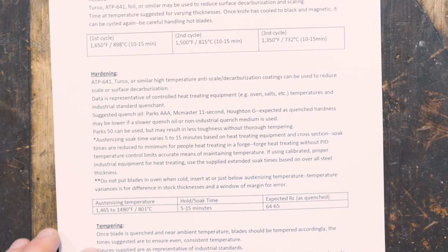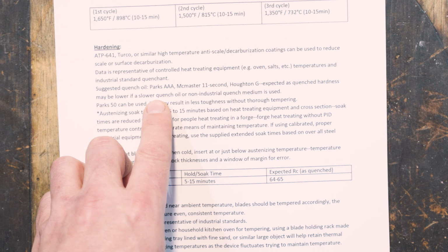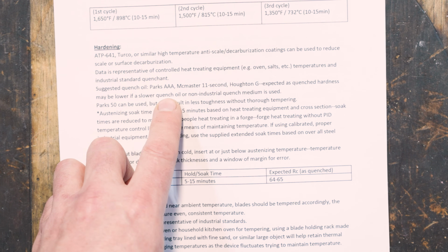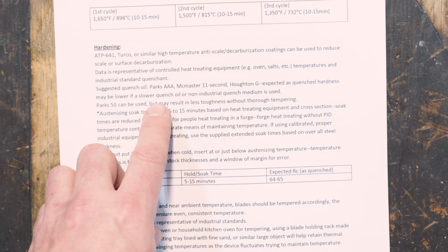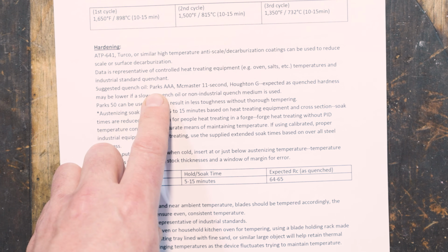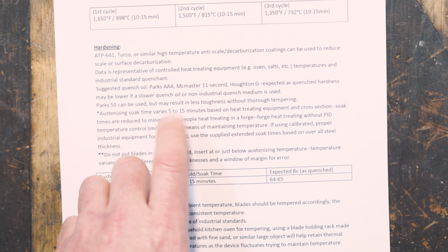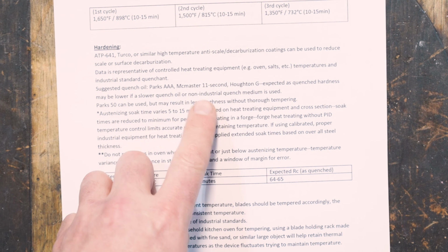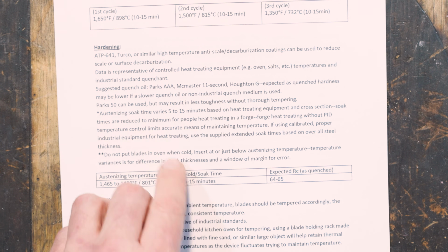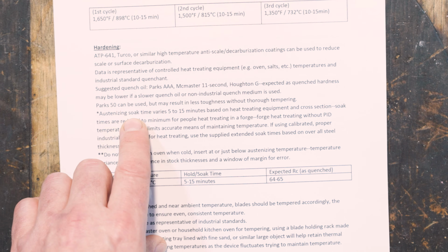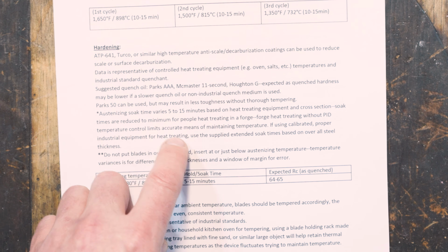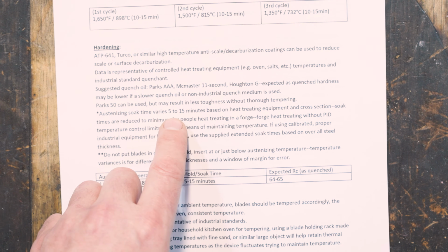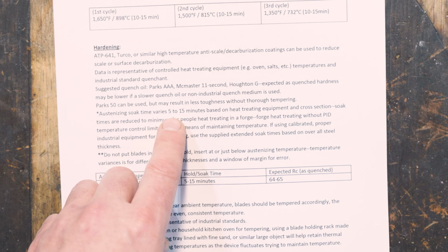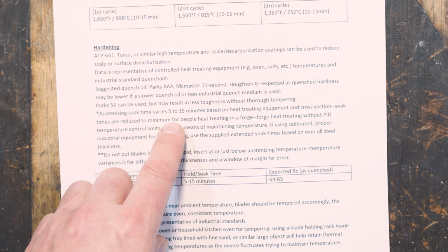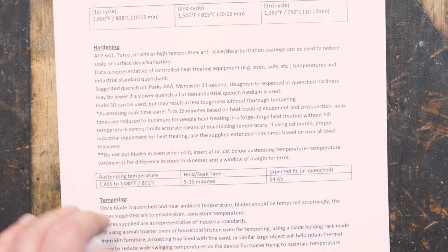So after we've done that, we're going to use Parks AAA as the quenchant, and we're going to heat that up to about 120 degrees. It doesn't say anything about that in here, but that's typically what I do. So the austenitizing soak, 5 to 15 minutes it says. So I typically would go like 10 minutes, just go in between there. And then if you need to go a little longer, you know, whatever, you've got that.